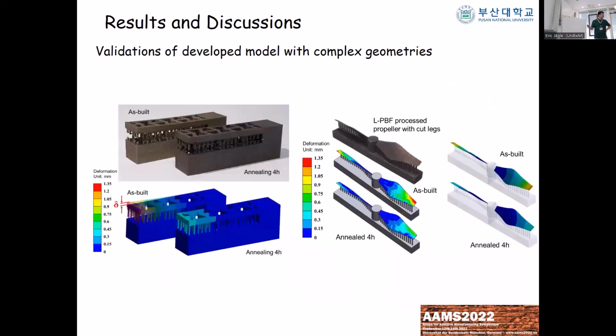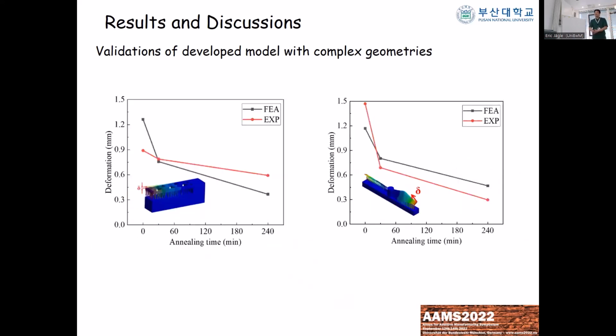And this is the final result. So this is the auxetic structure without and with the annealing heat treatment, and this is the simulation. This represents the deformation behavior very well quantitatively, and here is the deformation of the propeller shape in the as-built condition and annealing condition, and this is the experimentally measured deformation by the 3D scanner, and here is the predictive model, and we can see that the distortion agrees very well. And this is a quantitative comparison between the experiment and the simulation for the distortion at here and here.